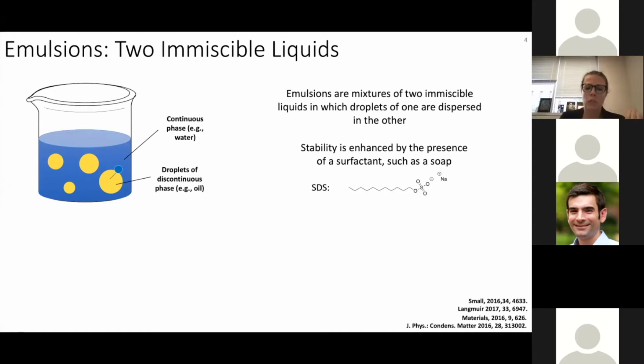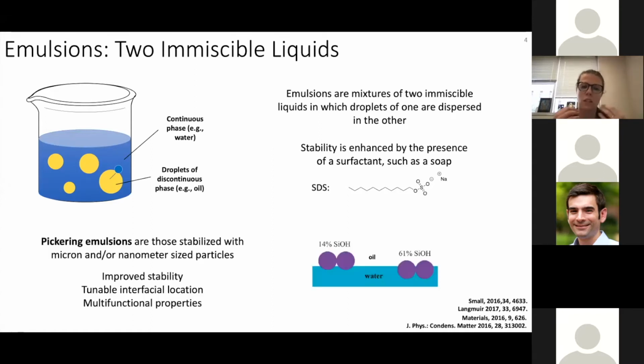And my group is specifically interested in using solid particles as the surfactant. In this case, we don't have an amphiphilic molecule, but instead we have a particle with suitable wettability that resides at the fluid-fluid interface. An example is silica particles, which, as prepared or as purchased, are covered with silanol groups and are very hydrophilic.